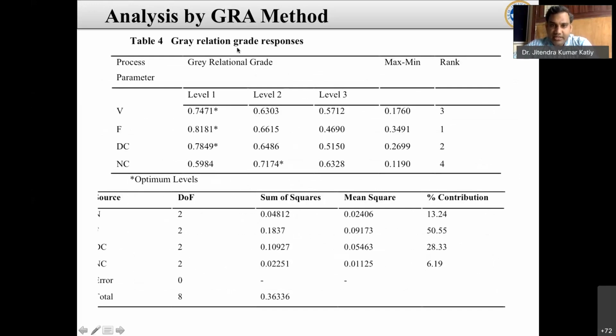Which response is better, and which contributes more? That we also optimized using gray relational analysis. This is the velocity in RPM, and it contributed only 13%. Feed contributed more in the force and surface roughness analysis. After that, depth of cut is very important. Nanoparticle concentration is also important, but less than the other three parameters.